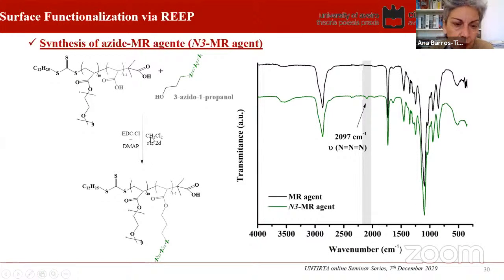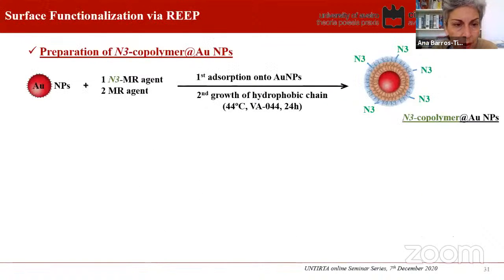So to do that, as I said, we had to adjust a little bit the composition of our macro-RAFT agent. So besides the PEGA, we had to add a few, very small number actually, of acrylic acid, which was then functionalized with 3-azidopropanol, and this requires monitorization, of course, to double check that the azide group was anchored onto the nanoparticles, or onto the polymer, in fact, and then proceed with the functionalization with the biotin.